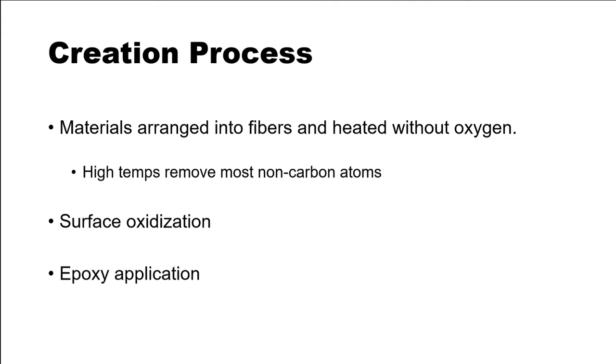And so the high temps are to expel most of the non-carbon atoms. And this gives you an almost pure carbon content material. So once you have all the strands or the fibers, you will weave them together, and then the surface has to be oxidized. And the reason for that is for the next step, which is the epoxy application.